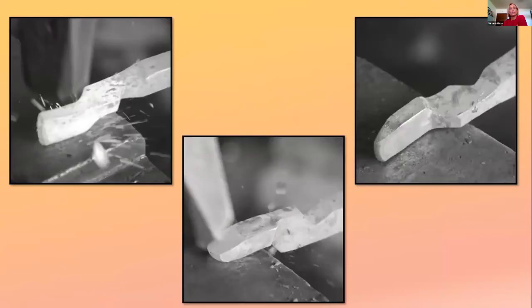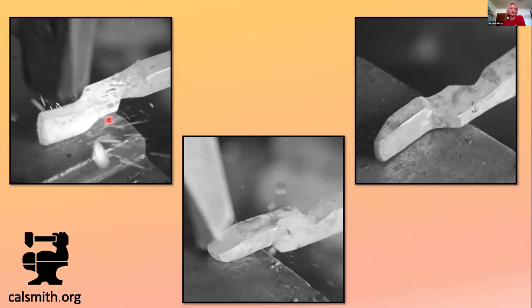Once you have your boss dressed, it's time to dress the jaw. You do that by bringing in the sides. For this project, it's going to be down to a three-quarter inch width and setting a slight taper on the end. You can really see the taper here. To get that taper in there, you're going to bring in the toes just a little bit first because as you hit the taper, you're going to get growth from side to side. It's going to grow in width. So bring in the toes to set that taper and end up back at your three-quarter inch wide. And then you can go back and dress the sides and finish off this whole jaw section.